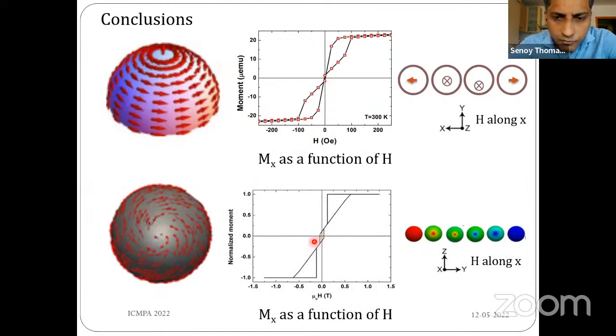due to the flipping of core magnetization, there is a possibility to get a hysteresis in the MH curve. This is one of the characteristics associated with the 3D spin configurations, where the core magnetization is pointing along the field direction. If you decrease the field and increase the field in the opposite direction, the core magnetization will flip, and this eventually results in a hysteresis.